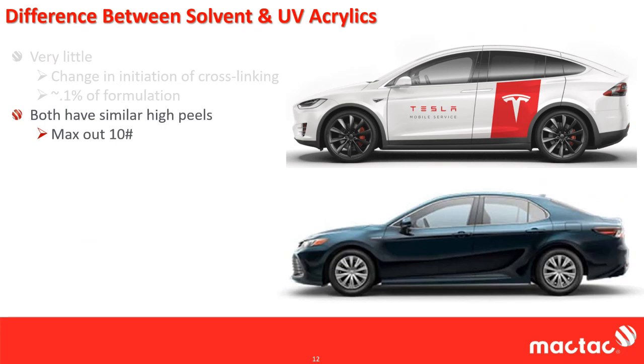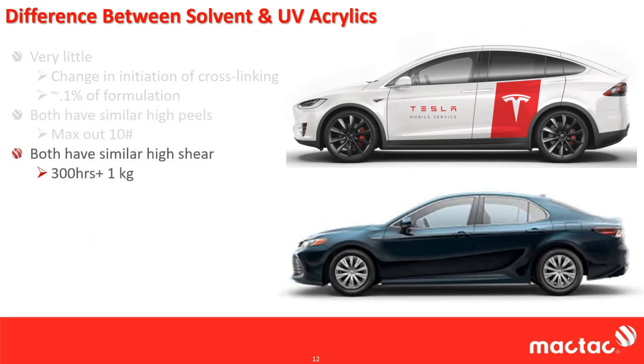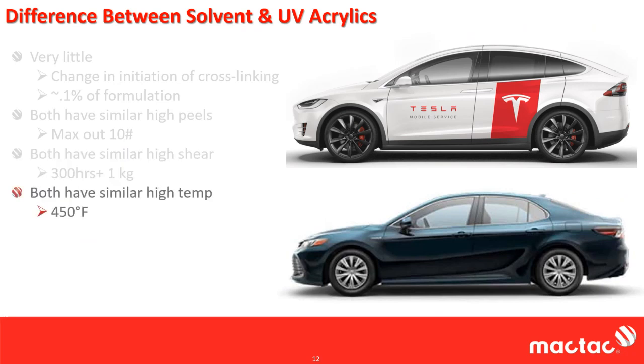In general, acrylics themselves, in general, solvent or UV, max out at about 10 pounds of peel. There are UV and solvent acrylics out there that have high shear. For us, 300 hours, we say 300 plus hours at a kilogram. Basically, at 300 hours, we give up. We take the shear down because we just assume it's not going to fail. So that's essentially maxing out the test. And we can max out those shear tests with UV, and we can max it out with solvent-based adhesives.